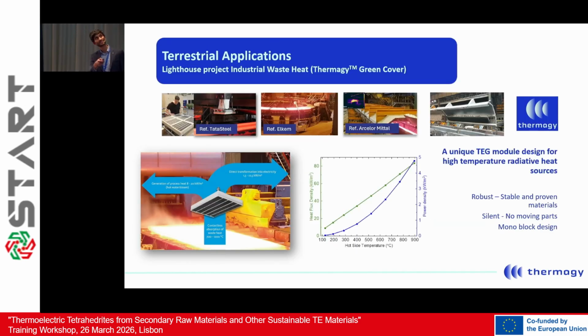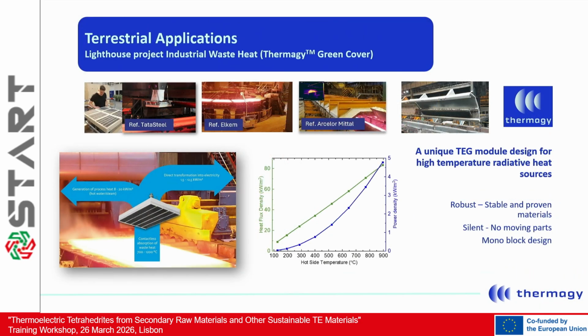Here you can see some nice pictures of our TEG panels. That's quite a large panel that we have tested at Tata Steel on top of their steel slabs, where we got really high temperatures on the hot side to get power out of our devices. Here we have also worked with Elkem in their silicon manufacturing plant, as well as ArcelorMittal, where you can see we developed a system to channel the heat towards our devices.